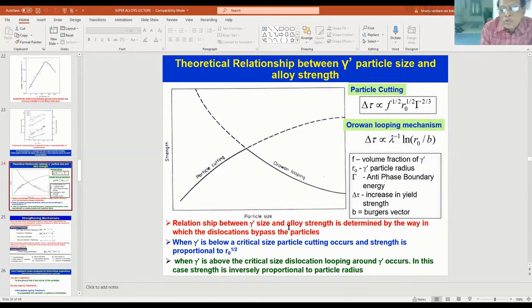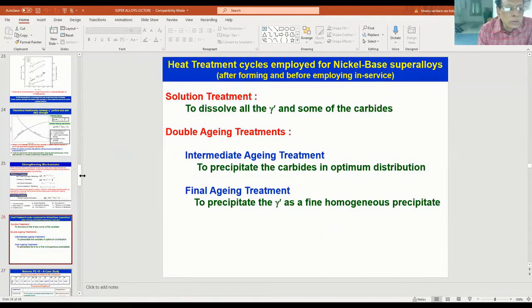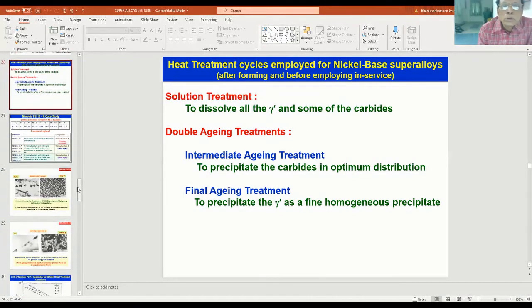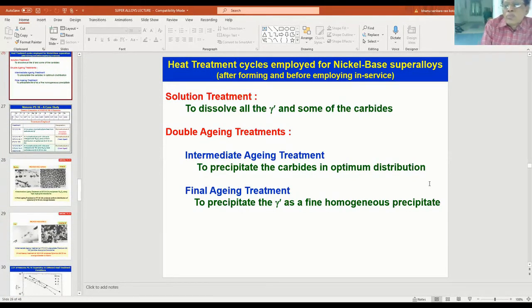The relationship between gamma prime size and alloy strength is determined by the way in which the dislocations bypass the particles, whether it's particle cutting or looping. When gamma prime is below a critical size, particle cutting occurs, and strength is proportional to R raised to a power. When gamma prime is above the critical size, dislocation looping around gamma prime occurs. In this case, strength is inversely proportional to particle radius. This is very, very important.